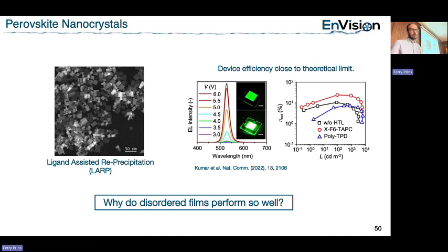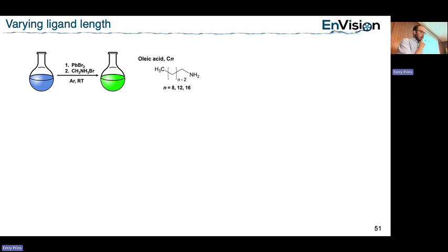Basically here, the synthesis is very simple. We do it at room temperature, even though there's a flask - we do it under argon just for consistency. We synthesize this methylammonium bromide perovskite phase nanocrystals, with oleic acid, and we have the capping ligands, 3 different types: either 8 carbons, 12 carbons, or 16 carbons. So we're making the alkyl chain a little bit longer.